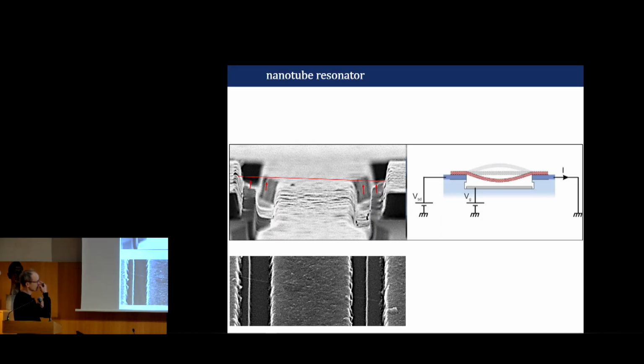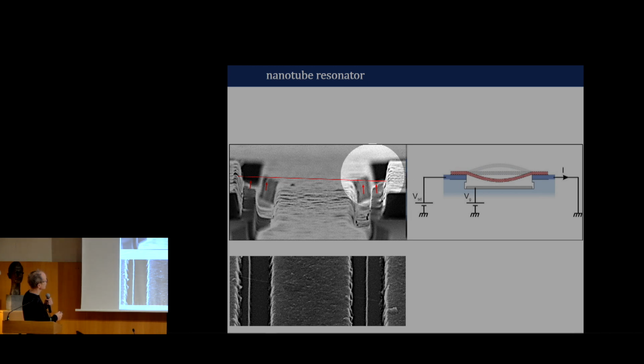Okay, so I come back to the experiments that are carried out in my group. Here in red, we have a carbon nanotube resonator. The nanotube in red is suspended over the trench. It has a diameter of about 1 nanometer, and it vibrates like a guitar string.